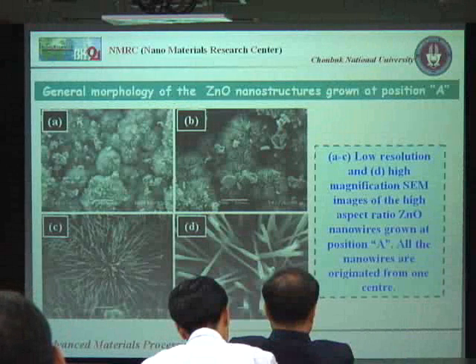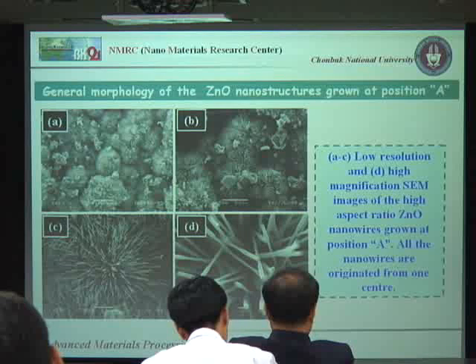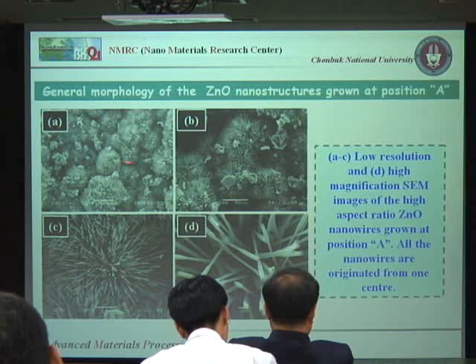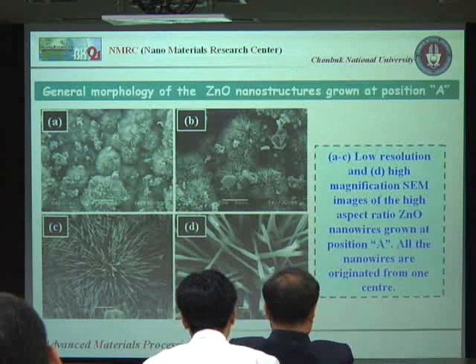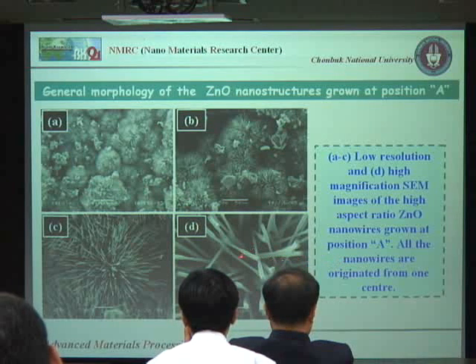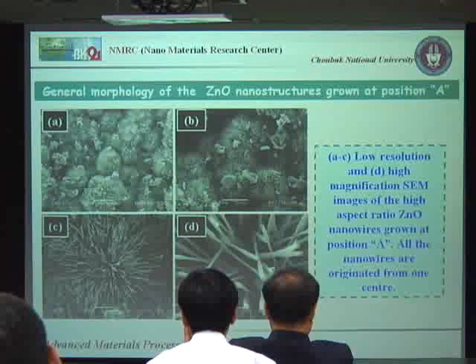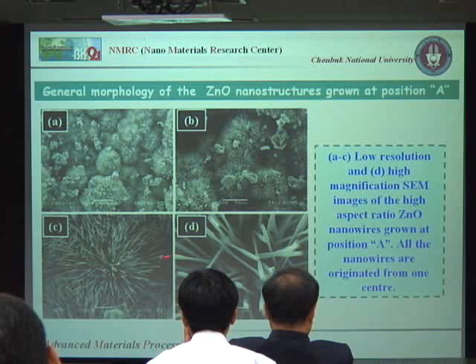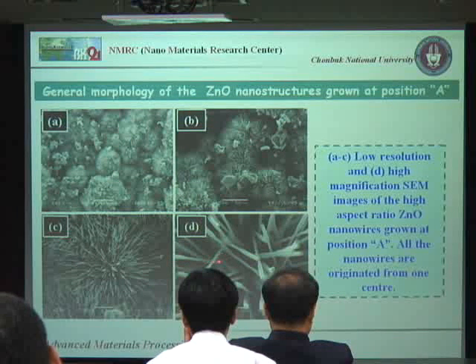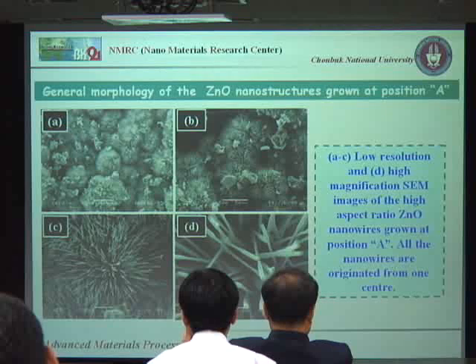So we got some interesting morphologies on different substrates, depending on the temperature of the substrate. At position A, we got urchin-like structures. It contains a high density of zinc oxide nanowires with a high aspect ratio. We can see clearly that these zinc oxide nanowires have well-defined hexagonal facets. It is also very interesting to note that the diameter of these nanowires in the lower portion is lower than in the upper portion. This upper portion diameter is increasing as we increase the distance between the source and the substrate.